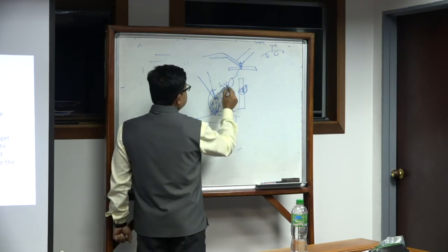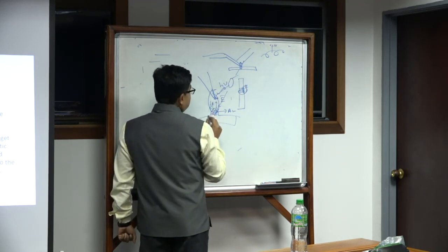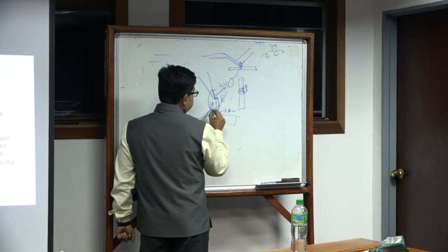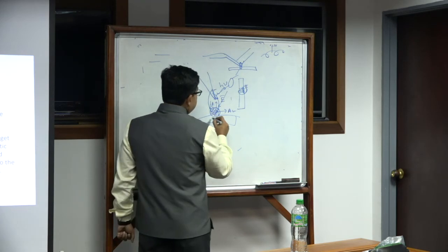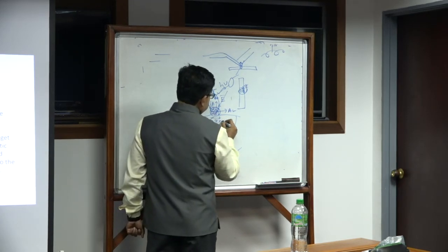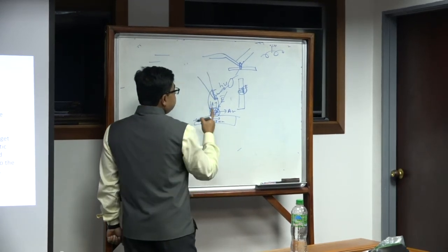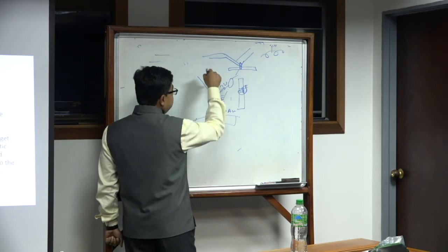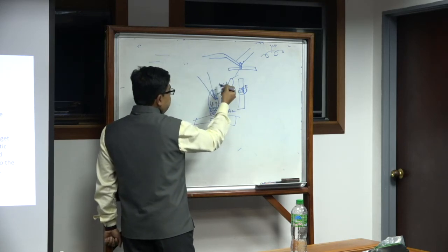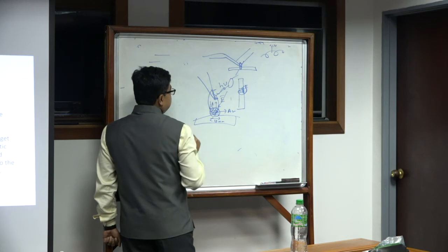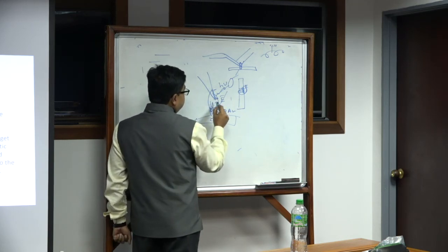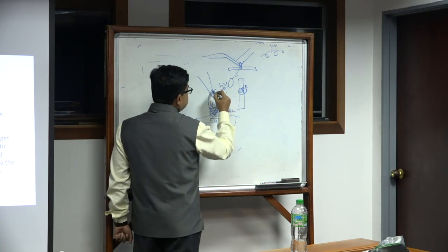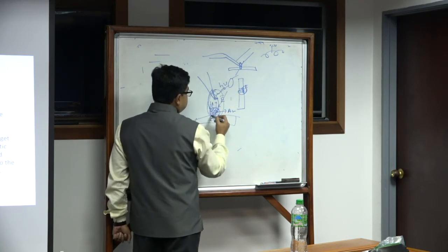So if I can capture the light which is scattering back, that means I am only capturing light which is coming from this small volume. Now this volume can be tens of nanometers. So I create a situation where I bring a metal tip and excite that tip with a laser, and the tip is in the very vicinity of the near field, meaning the light is actually illuminating the tip as well as the whole thing. This is the whole system.